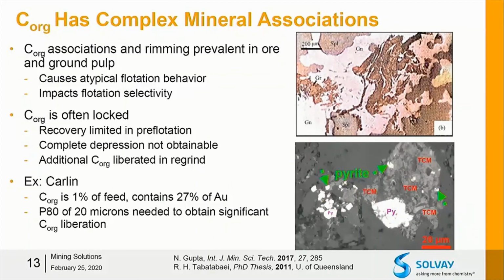And on the bottom, you see, again, a double refractory gold ore, or again, carbonaceous matter and pyrite, both of which actually carry gold values, are very intimately associated. Now, another factor with this that's actually coupled with the actual particle size of carbon being so fine is that carbon is very frequently locked, either in values or in gangue. And so because of this, recovery can actually be very limited in pre-flotation. Most pre-flotation circuits achieve maybe 25% carbon recovery for very good mineralogical reasons.